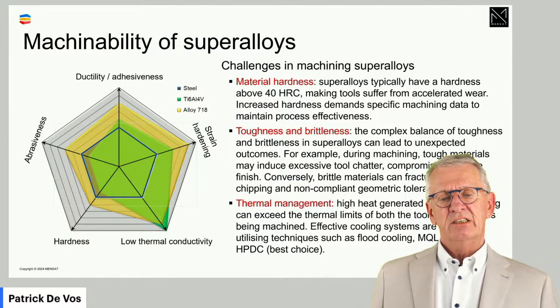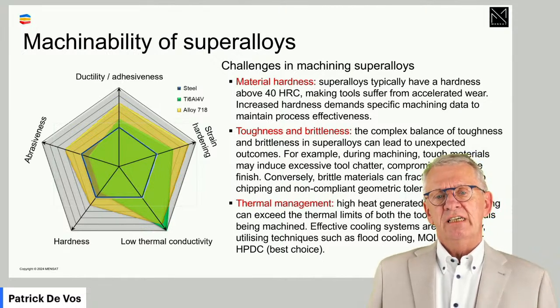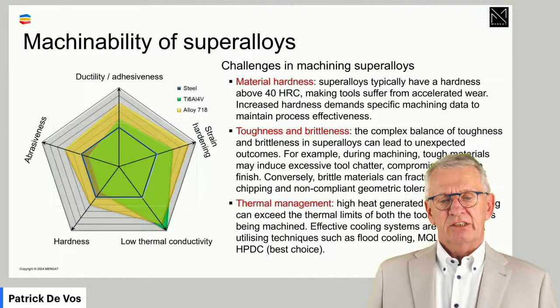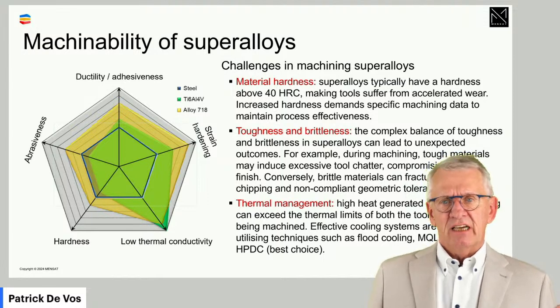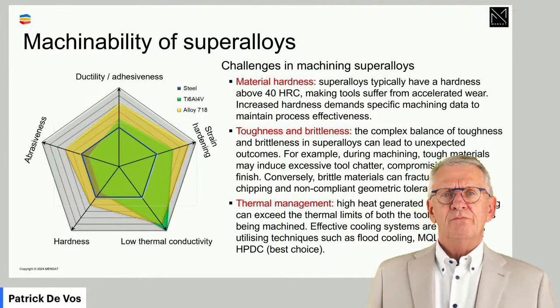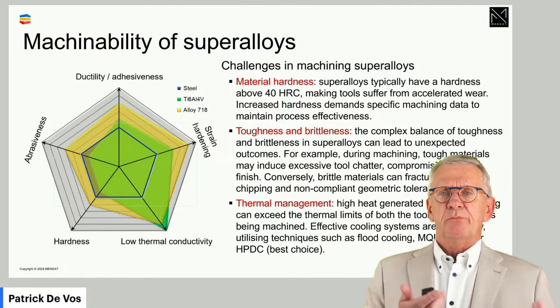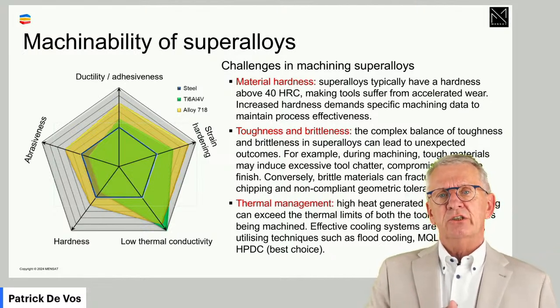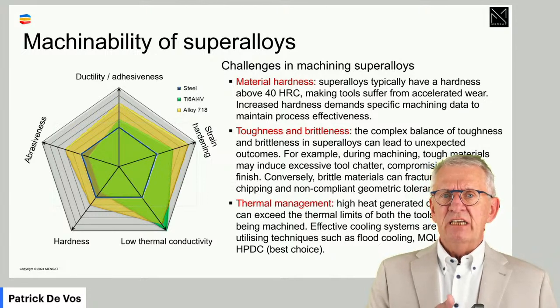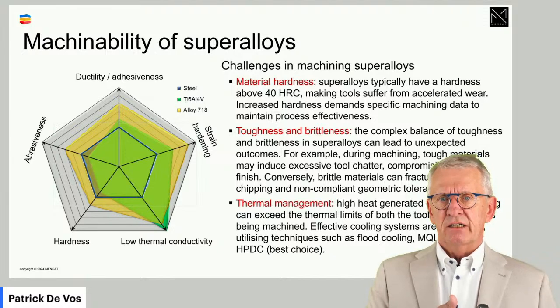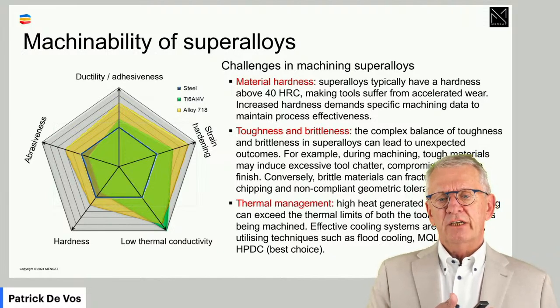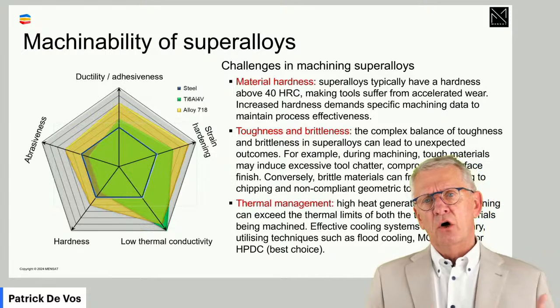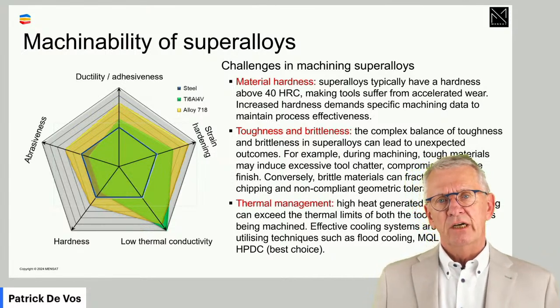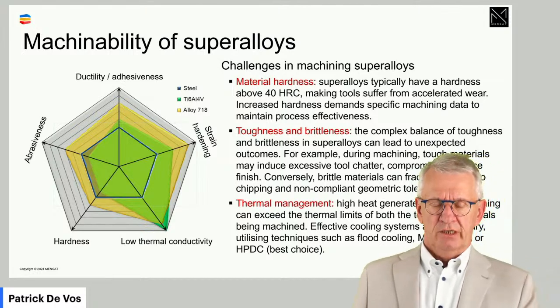What we see then is that compared to steel, hardness, abrasiveness, ductility, adhesiveness are all to a bigger extent present in a superalloy than in traditional steel materials. If you look to the green part, titanium is less demanding there. If you look, on the other hand, to strain hardening and low thermal conductivity, a low ability to evacuate heat away, we see very big differences.